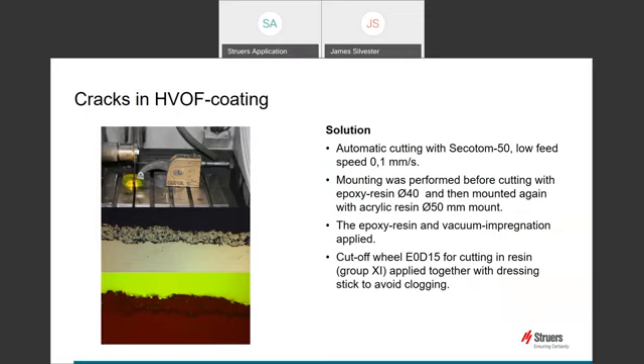Another consideration we had to make when we cut the coated samples is what cutting wheel to choose. If the whole sample was made of the coating material in this case, we may well have just used a diamond cutting blade. However, with the bulk of this material actually being steel in this case, it would cause unnecessary damage to a diamond blade. So we're forced to choose between an expensive diamond wheel we know we will damage, or an abrasive wheel that will have a high wear rate on a very hard coating.